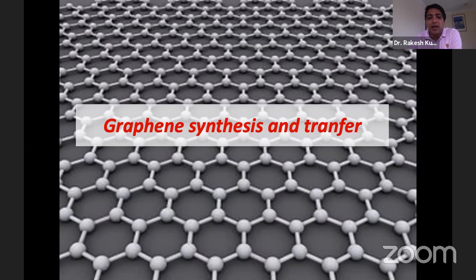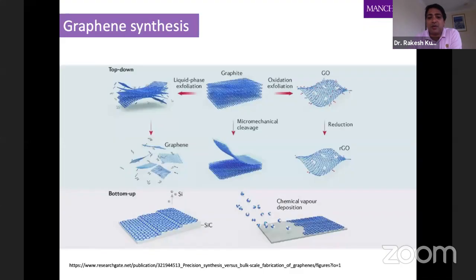So I'd like to go through some of the graphene synthesis and transfer methods. We cannot make large scale devices from a flake, and for a flake, you can only take a micron size flake from graphite. But in order to make large scale device fabrication, you really need graphene on a large area. There are different methods to synthesize graphene, either a top-down process or a bottom-up one. In the top-down, you start with graphite and then you apply either liquid phase exfoliation or an oxidation exfoliation method by which you break down graphite into individual graphene sheets.